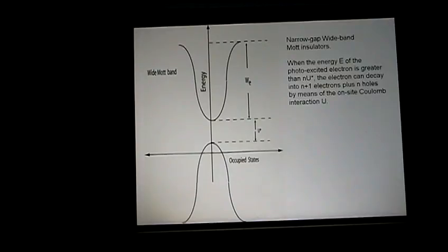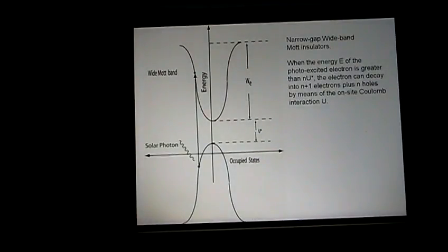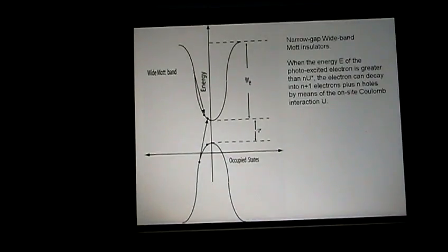If I'm in this scenario, then I don't need any other bands around, because when the photon comes in and photoexcites this electron-hole pair, the excitation will be vertical, because the photon cannot carry much momentum relative to the electron. Then I can have a decay process again, and I can be left with 2 quasi-holes and 2 quasi-electrons at the end of the day.